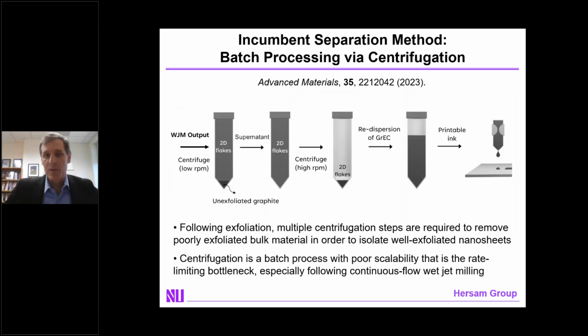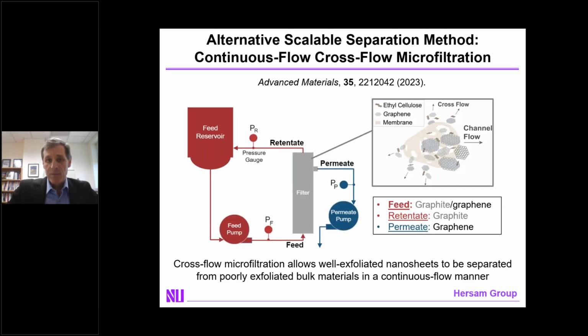The next step after you exfoliate is to isolate the well-exfoliated nanosheets from the poorly exfoliated bulk material. This has historically been done using centrifugation, which is also a batch process. And as a result, although the exfoliation is now continuous flow, we then slow everything down and have to do the separation using batch centrifugation. This method definitely works, but it becomes the clear rate limiting bottleneck, especially when the input is a continuous flow wet jet milling process. And as a result, I've been looking in our lab at alternatives to centrifugation.